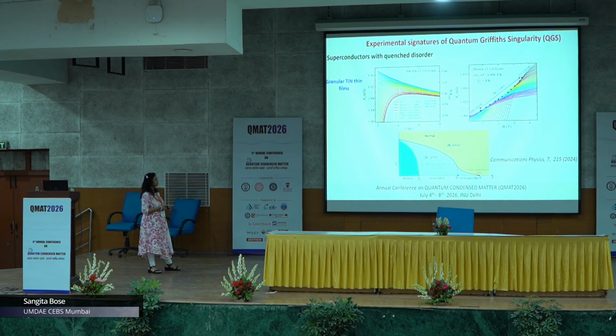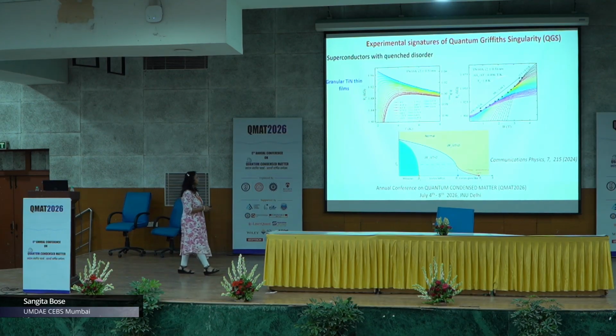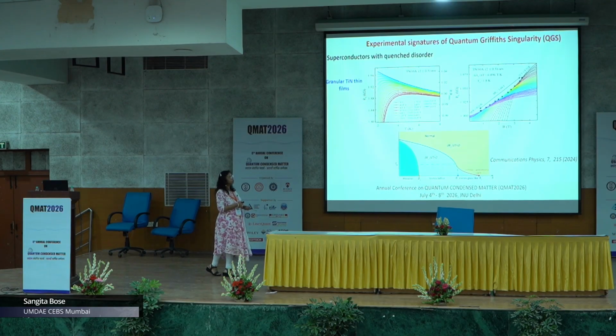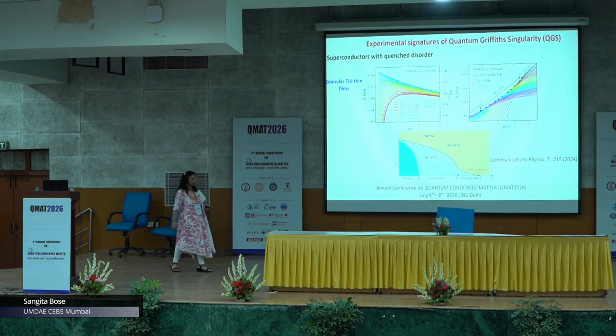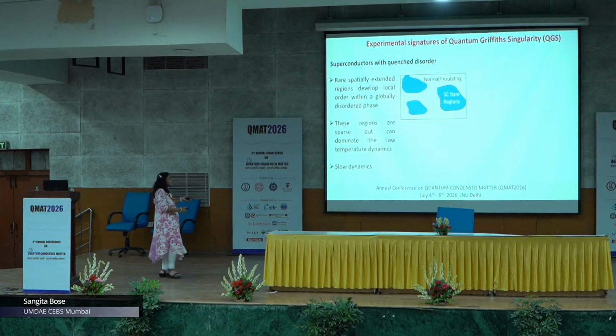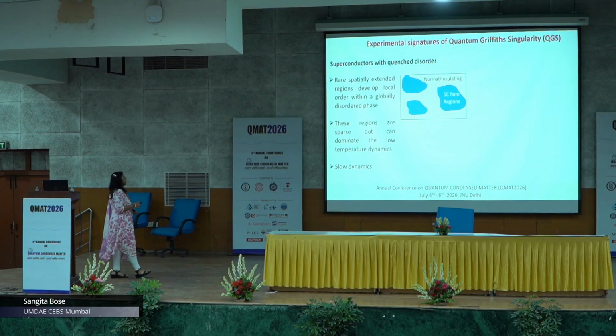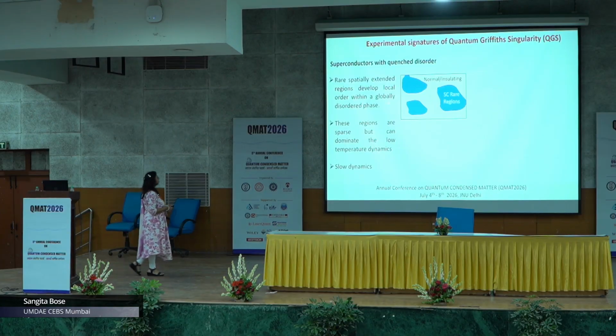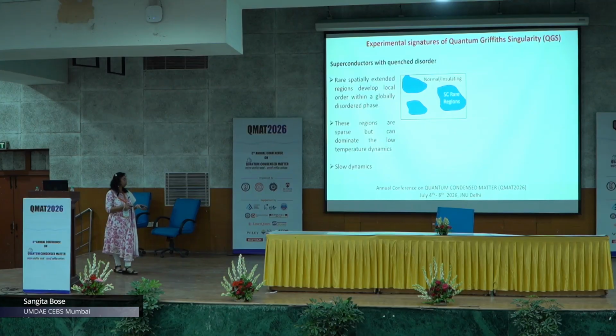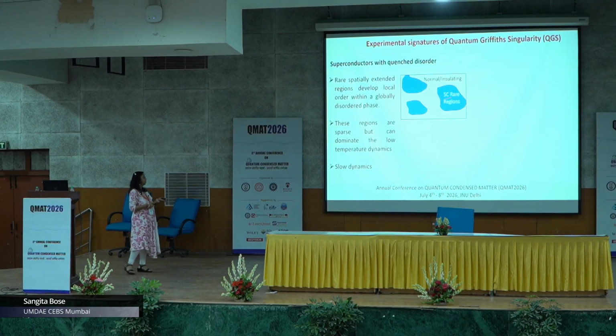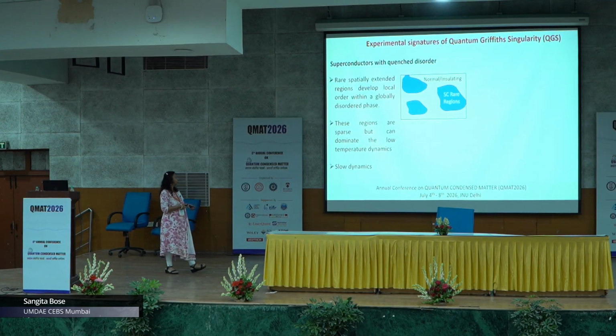So, for different temperatures, there are multiple crossing points, and this actually is the classic signature of a quantum-Griffiths singularity or the quantum-Griffiths phase which is formed. So, this is the phase which is formed over here, and this is what we will be looking at. So, how do we understand this phase? In superconductors with quenched disorder, what you actually form is some rare spatially extended regions which are ordered, and these rare regions are ones which show extremely slow dynamics, and these are the ones which start controlling your physics.